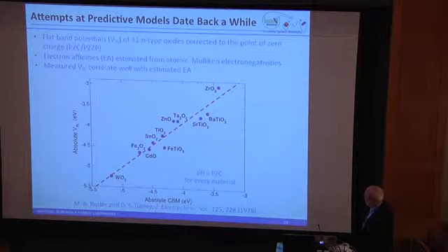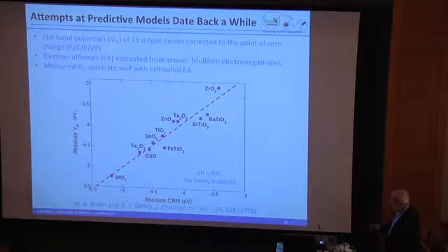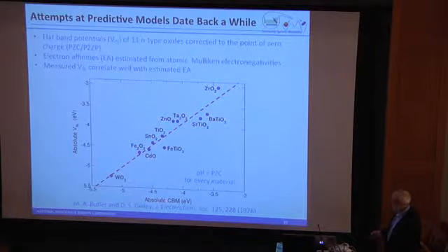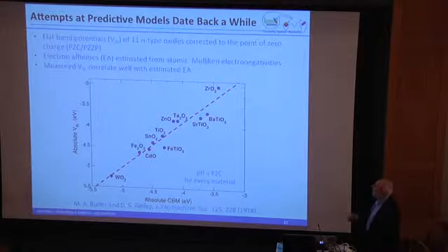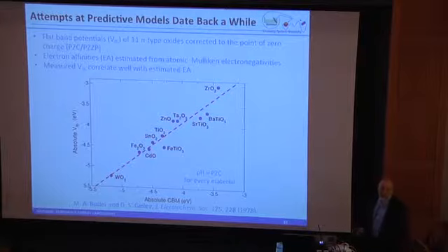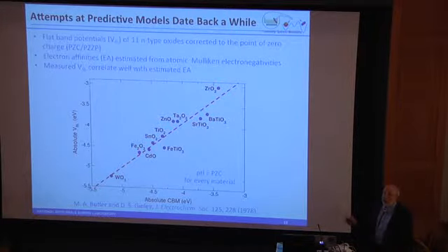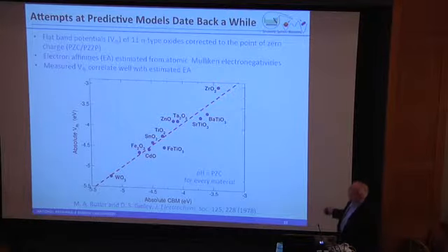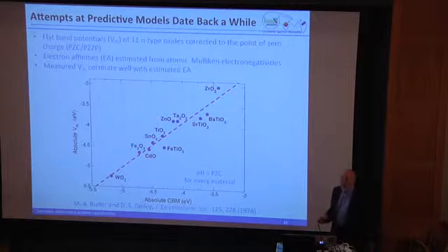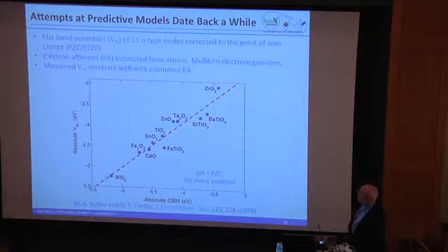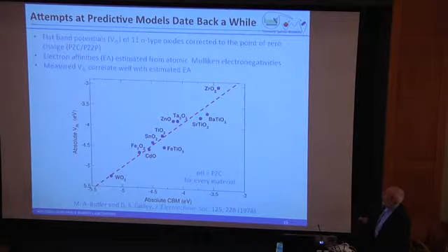So I told you I would show you that I'm really old, so I am. Back in the dawn of time, Mike Butler and I published a paper, in '78, on looking at the absolute flat band potential versus the conduction band minimum for a whole series of oxides. And we found, quite surprisingly, that when you correct all the energies to the point of zero charge, which is that point at which there's no adsorbed differential between hydroxides and protons, you get a wonderfully straight line for virtually all the oxides. And so why do I bring this up? Well, because this is the kind of correlation that we're obviously looking for, but we'd like to be able to derive it from first principles calculations instead of, in our case, empirical measurements that took me a couple of years to do. So how do we go about this?